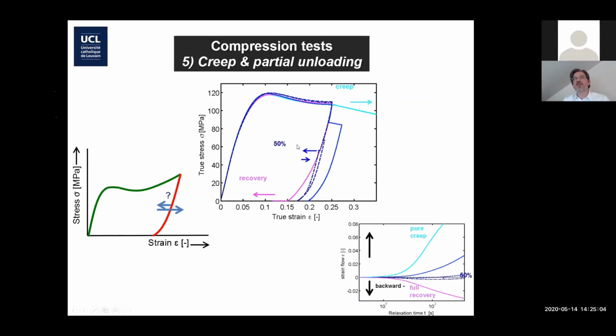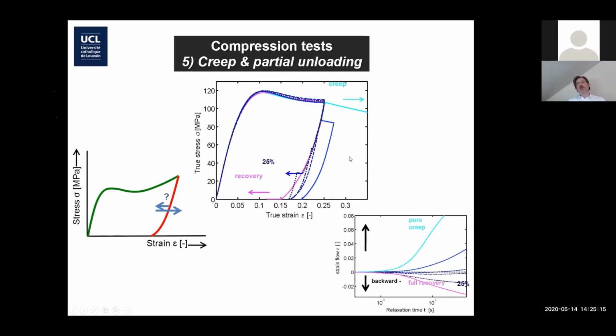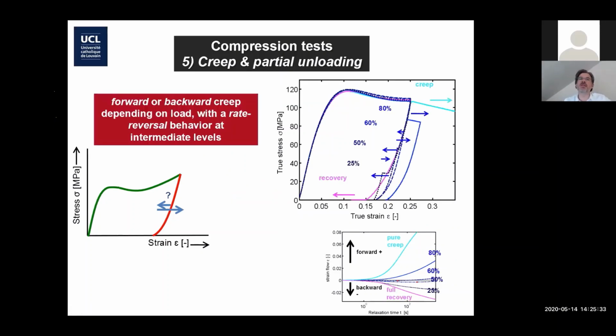If you do that at 50% force, 50% load, you get a lot more recovery, but at the end you're still having a little bit of creep. And then if you are at 25% load, you only see that if you maintain the stress at that level, even though you are under stress, the material elongates. It's a compression test. And then the material elongates. And at zero stress, we said you get recovery. So it's a very interesting phenomenon.